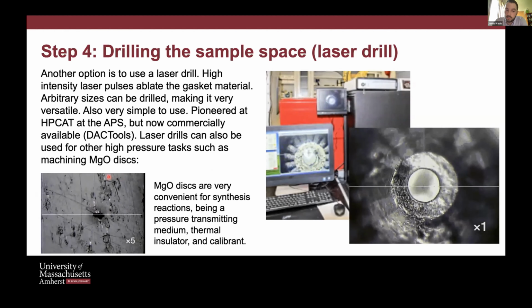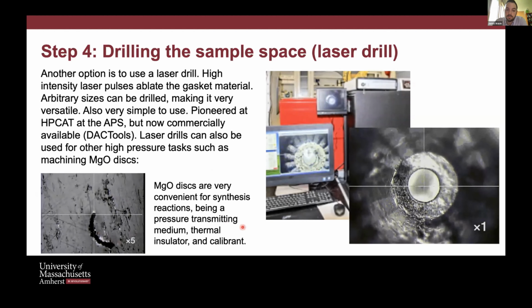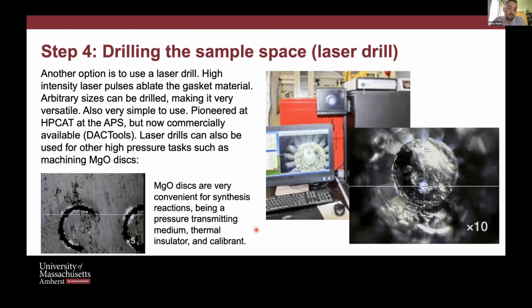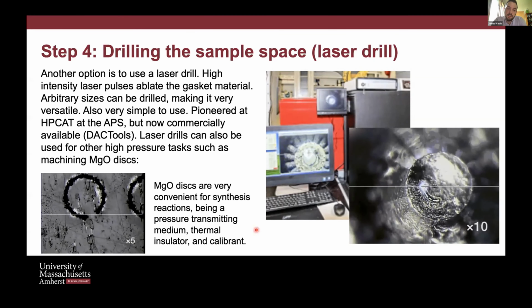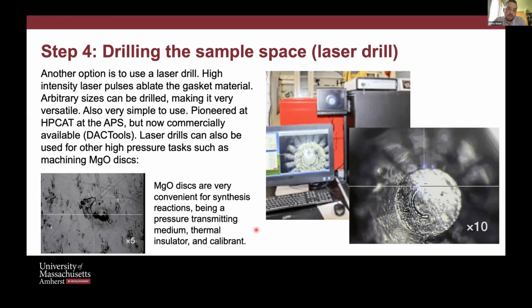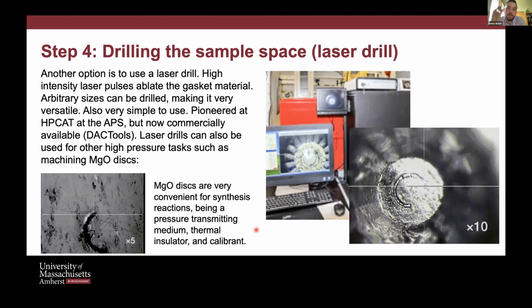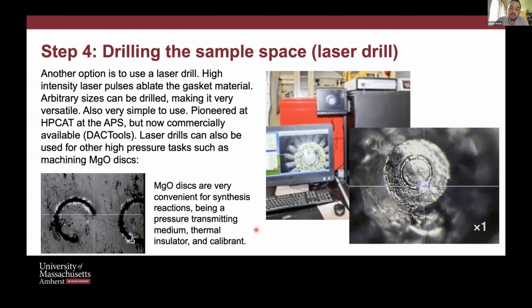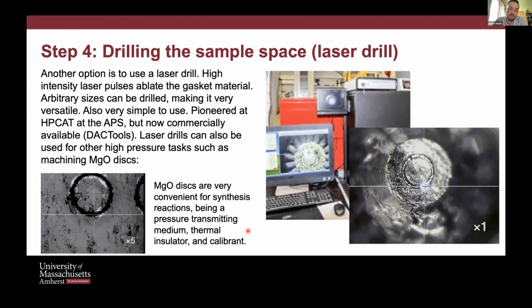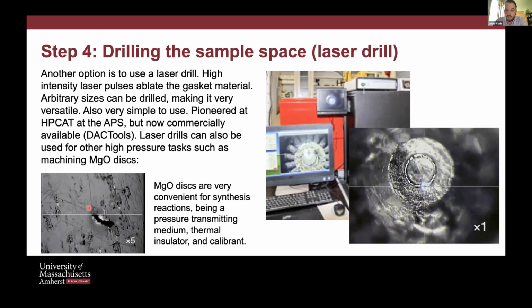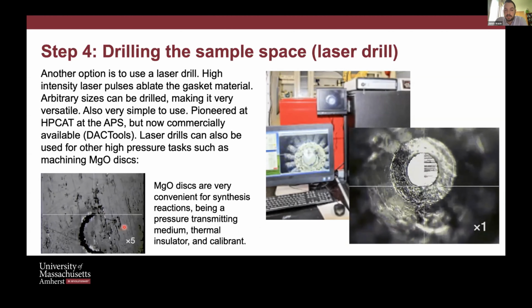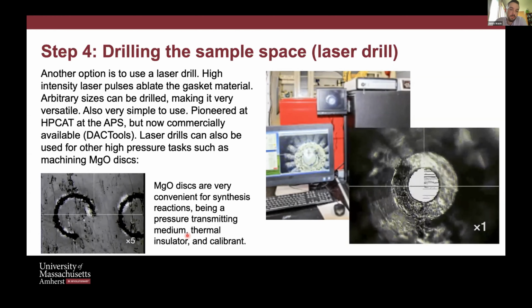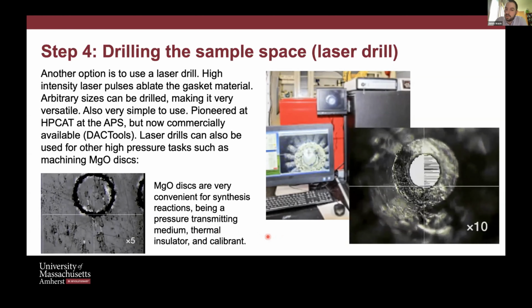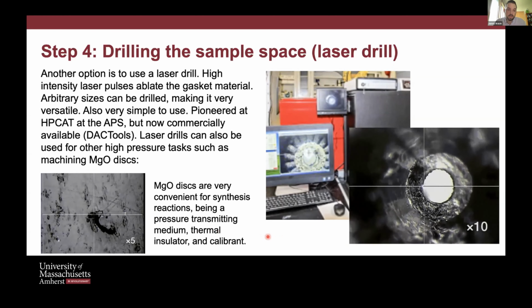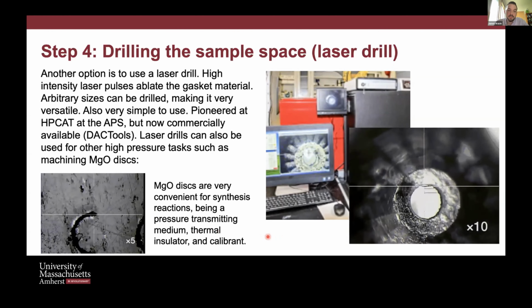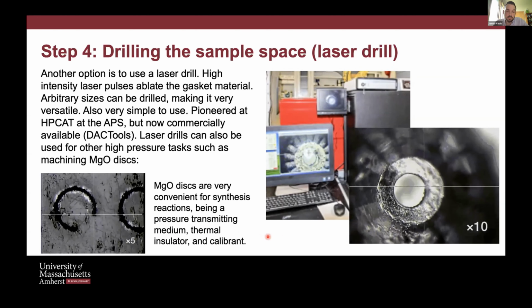We can also use it for other things in high pressure. So not so much of relevance probably to this audience, but we do a lot of synthesis at high pressure. That's not single crystal, so that's really powder. And so we like our pressure medium. We don't mind that it's not so hydrostatic. What we really need is thermal insulation, because we're laser heating. We don't want to heat the diamonds. And so this is just using the same tool to cut out discs of magnesium oxide, which we can then use as a pressure transmitting medium. It also makes it very simple to load in the glove box, because we're using solid pieces rather than messing with liquids and things like that.